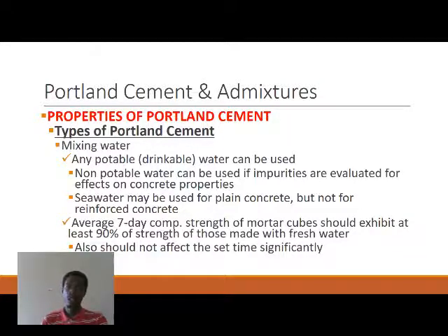You can use seawater, but it's usually not advisable with reinforced concrete because of the reaction of the water with the reinforcing steel. It begins to swell up. It's expected that at 7 days, any mortar cubes, remember we are talking about just cement now, should have achieved at least 90% of the strength of those made with potable water. And whatever you use should not affect the setting time.